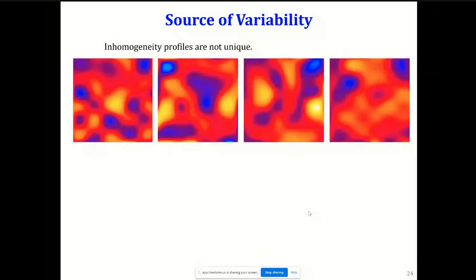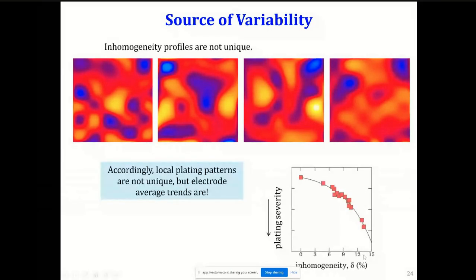Right? Now, again, with this, there is a source of variability as well, which is that these inhomogeneity profiles aren't unique. Even within the same electrode, if you image different sections, you are going to see a different pattern, right? And what it would give rise to is that if you look at the plating maps, the kind of maps I showed before, they would all look different and they would have signatures of what the local variation is, right? But there is still some solace in the fact that if you average over the entire electrode, things are still going to scale, right?